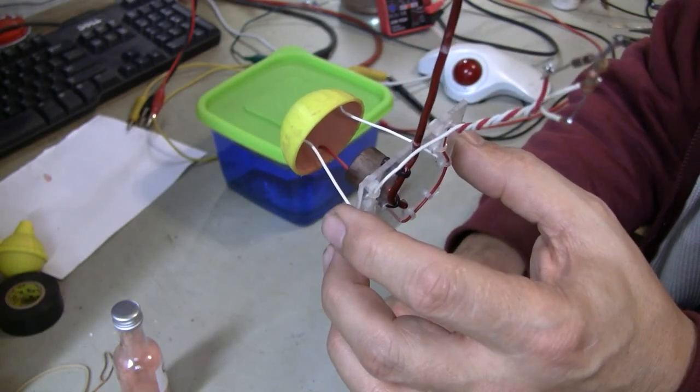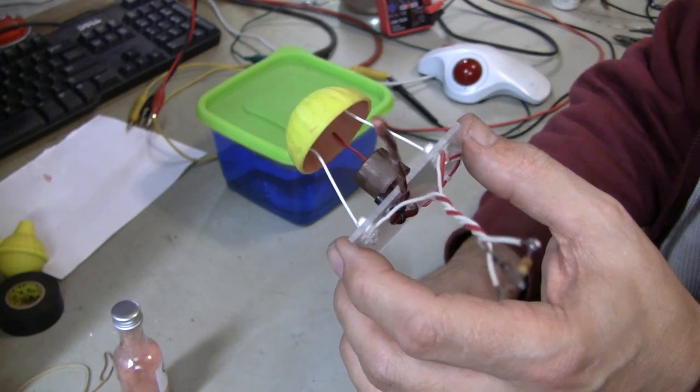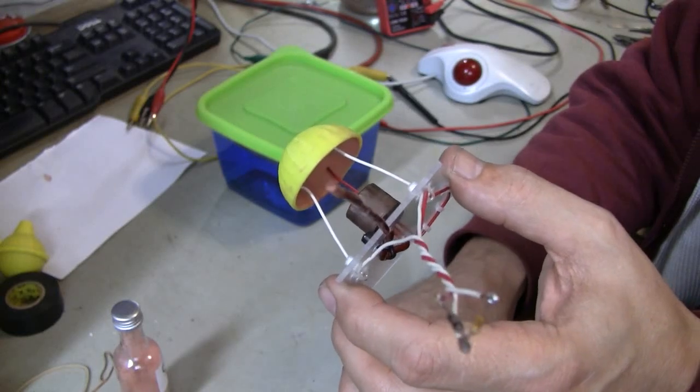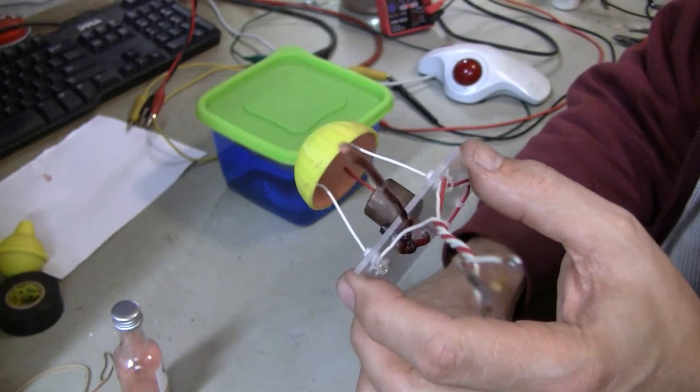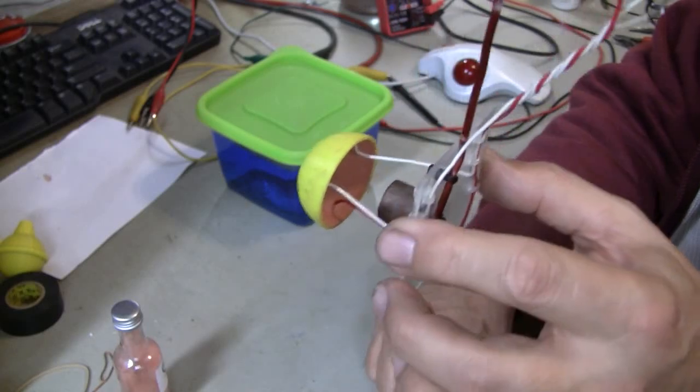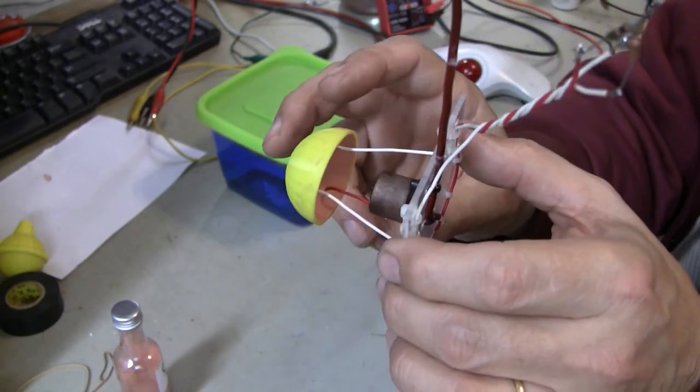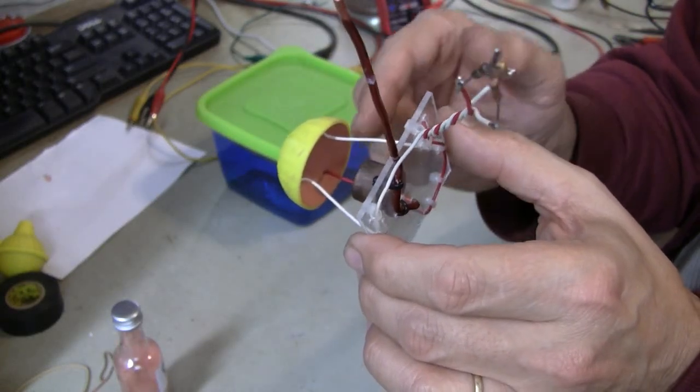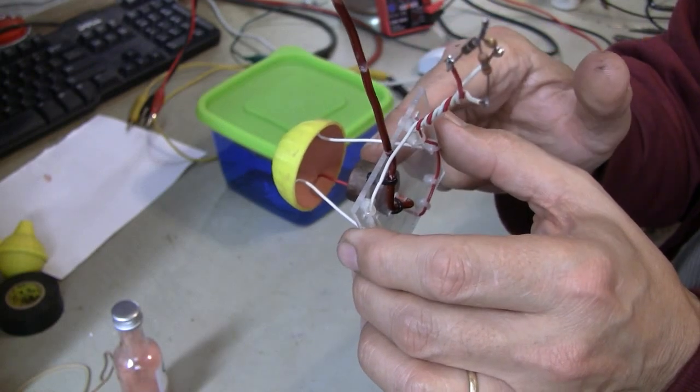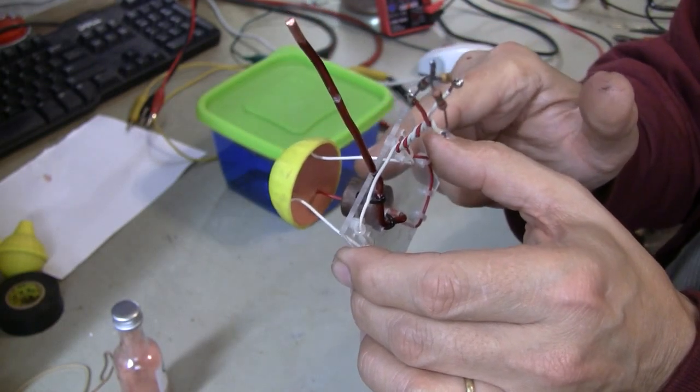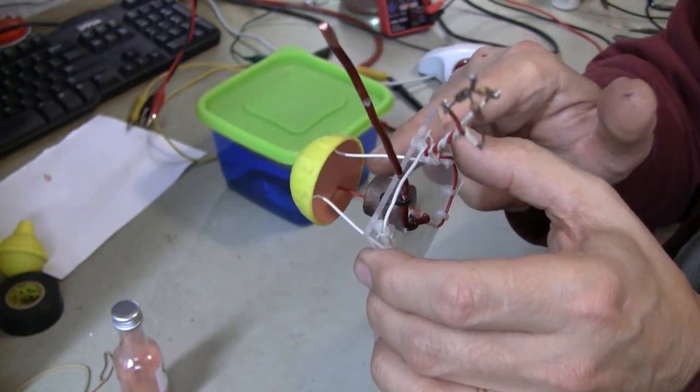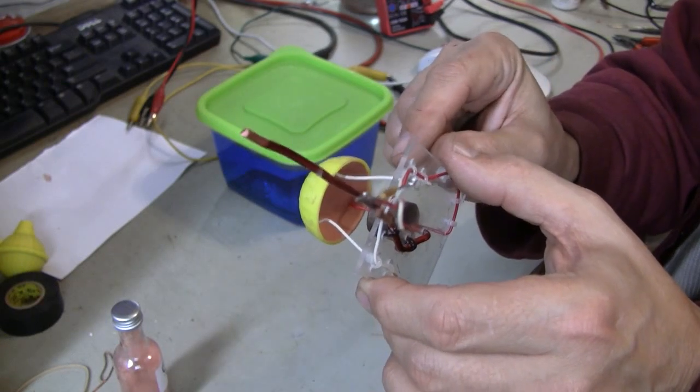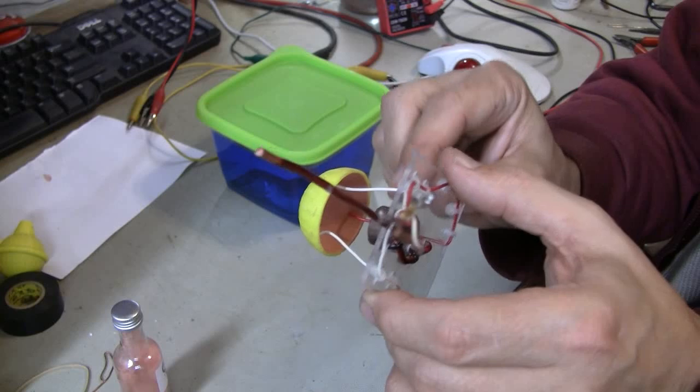And if you look at the way it spreads out, it's kind of like the way melanoma spreads out on the surface of someone's skin, quite frankly. It spreads out very rapidly from the point of contact to the rest of the ball and eventually forms one solid layer, one contiguous layer all the way across the inside wherever the copper powder has been laid in place. And then from then on, as you plate, it only becomes thicker and thicker rather than spreading out. But the spreading process takes place very quickly, that's the purpose of the powder.